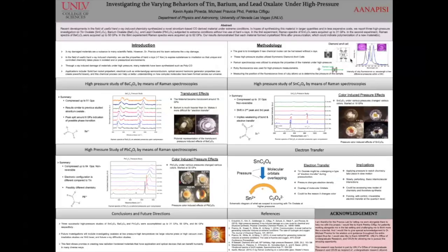All it is, is that there's a small cell containing a diamond in it. And then we place a small amount of material on a culet face. We also put a ruby in there so that we can measure pressure later on. We get another cell with another diamond in it. We close it up. And then just applying a small amount of force in the diamond anvil cells can generate large amounts of pressure. Gigapascals, which is 10,000 times larger than what we feel right now.